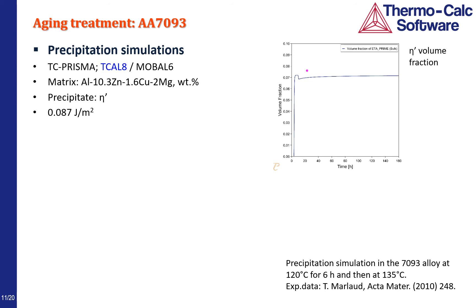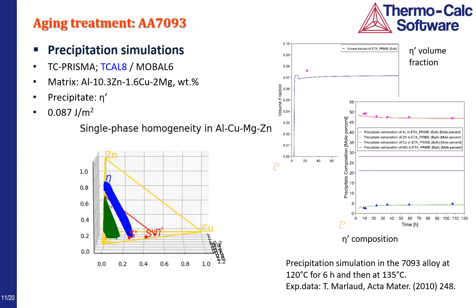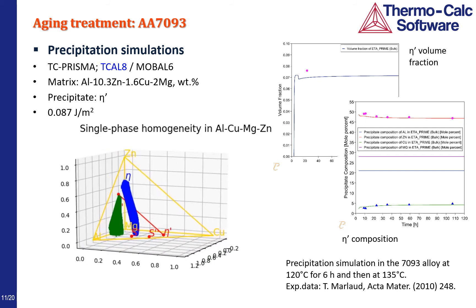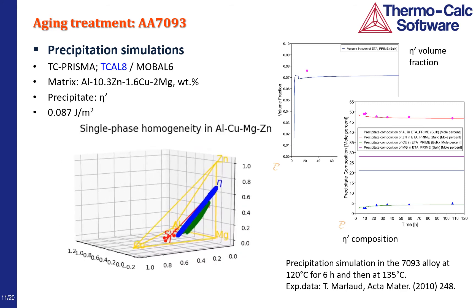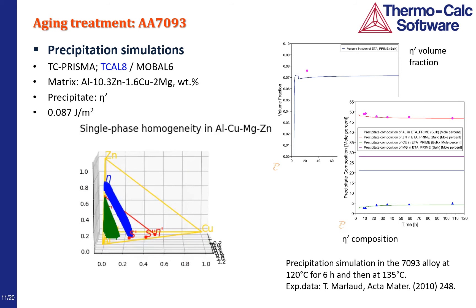We then investigated the aging treatment. Here we simulated the precipitation of the eta-prime phase in a two-stage aging treatment. The simulation was done with the TCAL8 database, which is to be released soon. The volume fraction of precipitates agrees with the data within experimental uncertainty. The kink in the curve indicates partial dissolution when the aging temperature was increased from 120 to 135 Celsius. The solute contents in the precipitates are well accounted for, especially the substitution of zinc atoms by copper atoms. The modeling of the eta-prime phase was done in the aluminum-copper-magnesium-zinc quaternary system, which is the basis of the 7000-series alloy. This video illustrates the homogeneity ranges of the eta-prime phase, T-prime, S-prime, S-double-prime, as well as the equilibrium T phase and the eta phase.